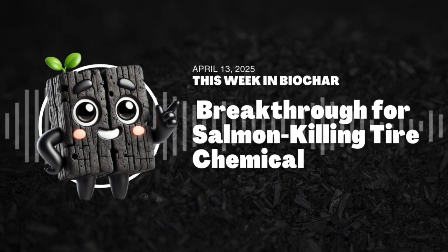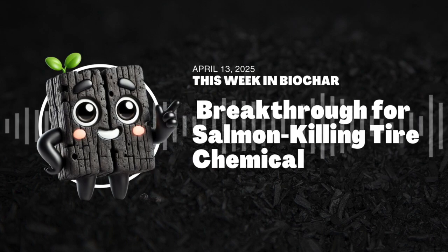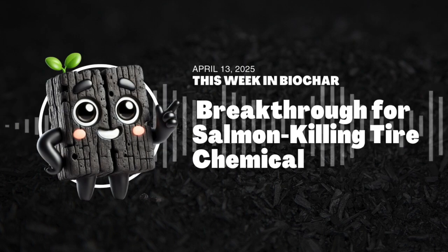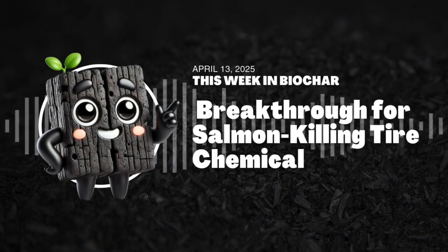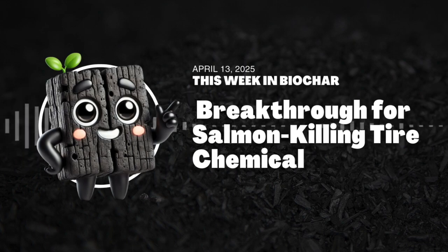It drops from around 38% down to 28%. That's quite a bit less biochar overall. It is, and that's the key decision point, isn't it? If you need really high-performance biochar for a specific, maybe high-value application like targeted pollution cleanup, or maybe those electrodes we'll talk about later, then maybe getting less biochar, but much better biochar, is worth it.